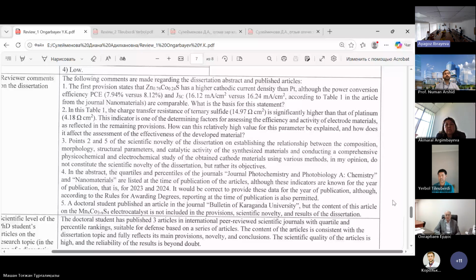Regarding question number 2, this can be explained by the different conductivity of zinc and cobalt-based sulfides. In zinc cobalt sulfides, only certain cobalt sites may contribute significantly to catalysis, while zinc-rich regions are less active, leading to slow interfacial charge transfer kinetics, since the concentration ratio of zinc to cobalt is 3:1, where zinc is higher. Zinc sulfide content improves stability. Also, the increased series resistance slightly affects DSSC performance. The ternary sulfide still shows good electrocatalytic activity and remains an efficient low-cost alternative to platinum counter electrodes.